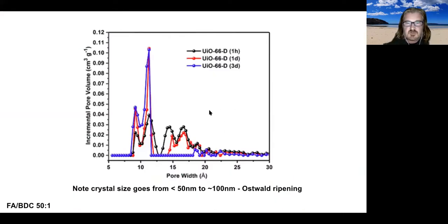It's a little more interesting than this, because if you look at the evolution, you can map out the pore size distribution as a function of the synthesis time. The black and the red parts of this plot highlight that there are large pores after 1 hour and 1 day respectively. But after 3 days, these large pores are absent, and these large pores are associated with those missing clusters. So this is telling us that as the synthesis time evolves, we essentially make the crystal more perfect. It's indirect evidence of Ostwald ripening, but we actually have more direct evidence of Ostwald ripening occurring.